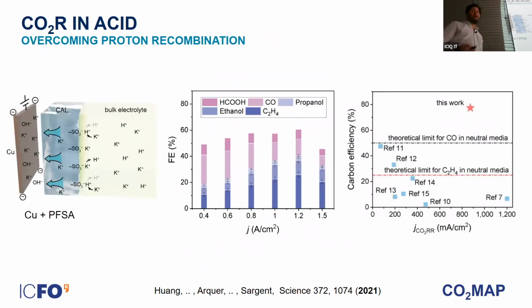So now, having found the key role of potassium in the system, we thought, okay, let's redesign the catalyst again in such a way that we could improve the local availability of potassium ions. So we thought of combining again the metallic copper catalyst with ionomers of the perfluorinated sulfonic acid family, in this case not Nafion, but a shorter ionomer which has slightly different properties, in such a way that this ionomer would preferentially exchange its hydrated domains with potassium and not with protons.